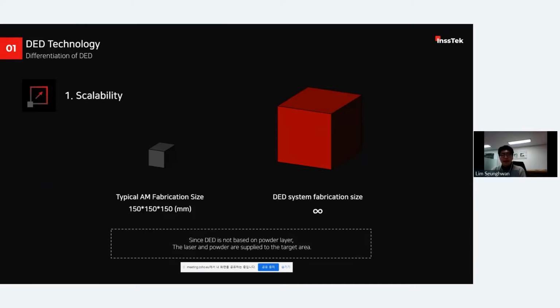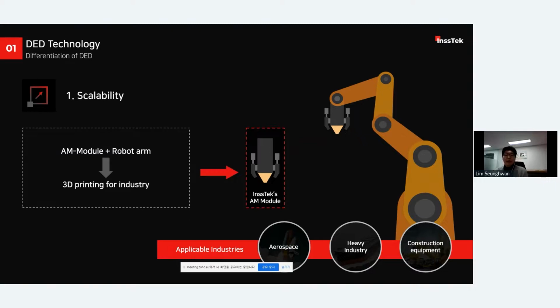The first one is scalability. Unlike powder bed fusion and binder jet methods, the DED method doesn't need a powder layer. It has a movable printing module that applies material and energy sources to the target point. Thus, its printing volume can be expanded to a comparatively large size. And also, if you use a larger beam size, printing speed is dramatically increased. A large beam size can contribute to this scalability. Also, the DED method and robot arms are a good match. Robot arms can control the motion of the printing module with a high degree of freedom and wide working range. This feature is especially competitive in industries that need large-sized parts. Of course, if you use multiple robot arms, productivity can be increased.